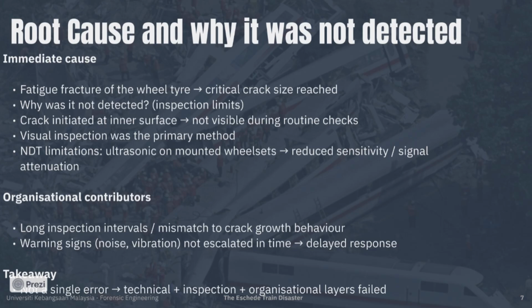The immediate cause was the fatigue fracture of the wheel tire after the crack grew to a critical size. The key forensic question is why it was not detected earlier. First, the crack initiated at an internal location on the inner surface. This is not visible during routine visual inspections, yet visual checks were the primary inspection method. Second, inspection capability had technical limits. Ultrasonic testing on mounted wheel sets can have reduced sensitivity because the axle-wheel interface attenuates the signal. This means smaller cracks may not be detected reliably, especially if inspection intervals are long.